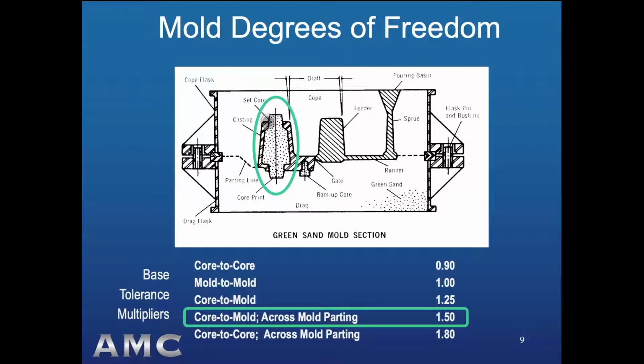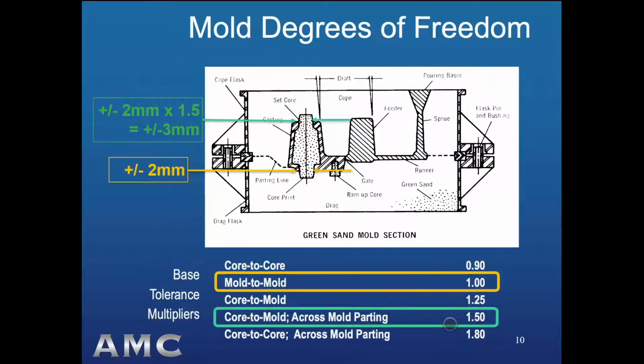The consequence of the variation in the mold assembly results in a tolerance coarsening of 150% or 1.5 times the base tolerance of the features formed in the bottom half of the mold only. So if the tolerance for the hole formed in the bottom of the tall core is plus or minus 2 millimeters, then the tolerance for the hole formed at the top of the core is 1.5 times that base tolerance, or it becomes plus or minus 3 millimeters.